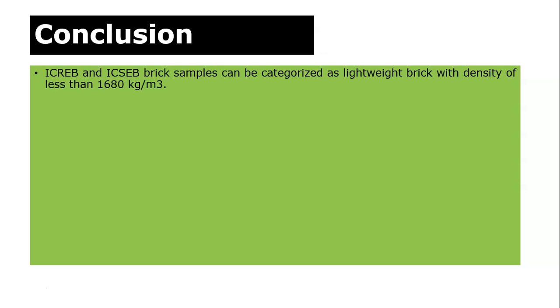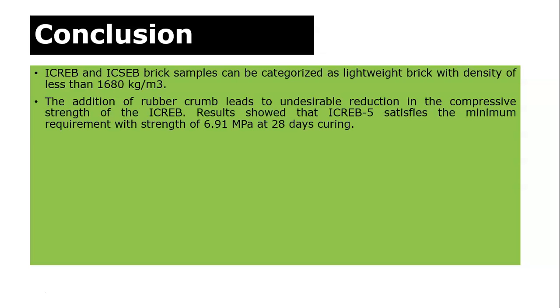Therefore, based on the results and standard requirements, it is concluded that the ICREB and ICSEB brick samples can be categorized as lightweight bricks with density of less than 1680 kg per cubic meter, and this result is favorable for easy handling and transportation, which saves fuel and energy. And the addition of rubber crumb leads to an undesirable reduction in the compressive strength of the ICREB. Results showed that the ICREB 5 satisfies the minimum requirement with strength of 6.91 MPa at 28 days curing.